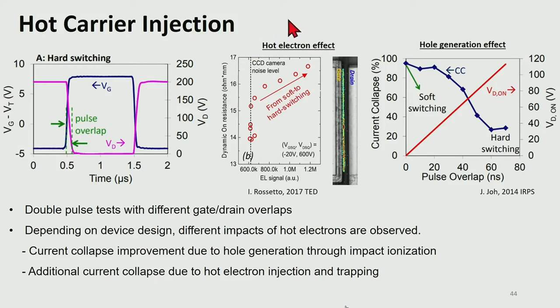But in some other cases, you may see a completely opposite case. If you see this right figure, now with increasing this overlap time, the dynamic RDS,on or current collapse performance is actually improved, which is a completely opposite result to the data shown in the center figure. This is because the hot electrons also can cause impact ionization, and holes generated in the impact ionization can compensate the trapped electrons and improve the dynamic RDS,on performance.